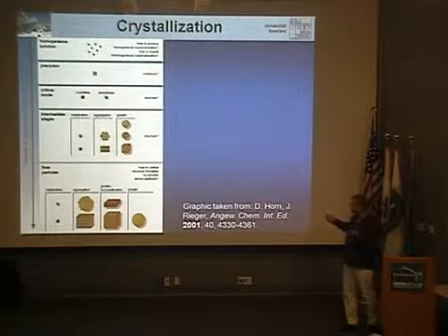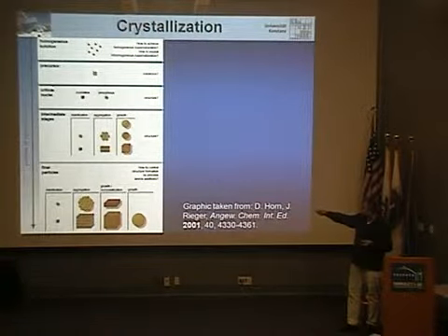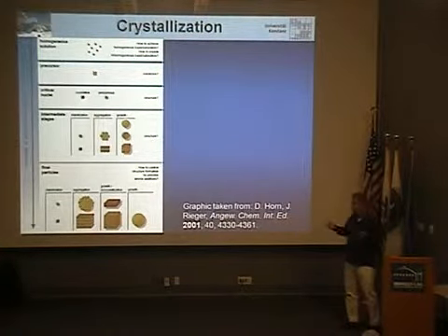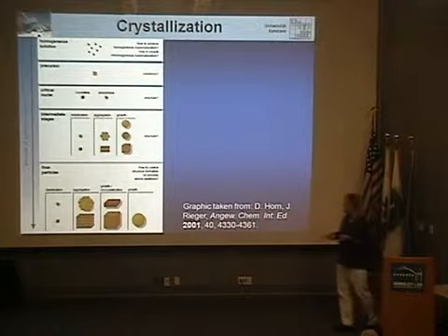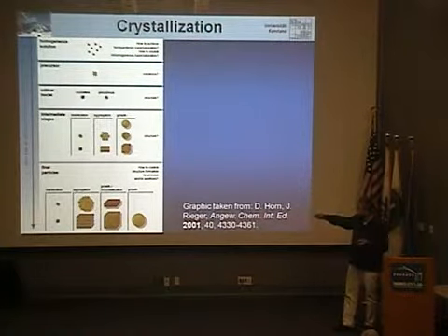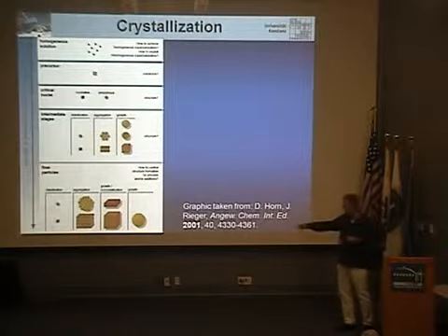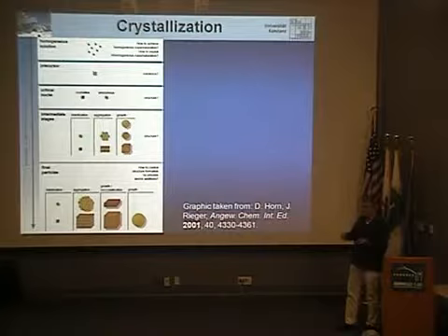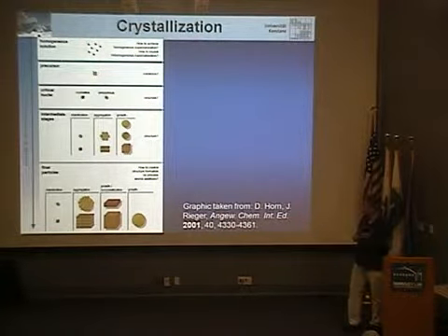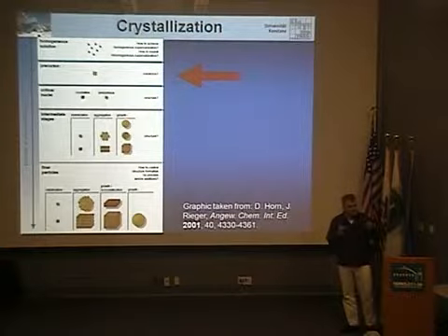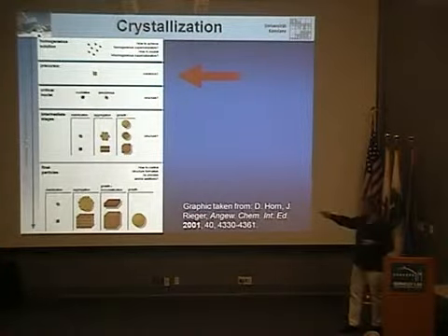So do I have precursor phases, yes or no, until I arrive at a critical crystal nuclei, which can be amorphous or crystalline. The structure also question mark, because it's very hard to investigate that analytically. And then you come to the intermediate stages where you can have growth of amorphous structures, crystalline structures, hybrid structures, or aggregation or stabilization of nanoparticles until you end up with a zoo of final species which you get in a mineralization event. And we were asking ourselves the question, what happens at the earliest stages, even before we form a critical crystal nucleus? What happens if I look at the ions on the pathway to the final crystal?